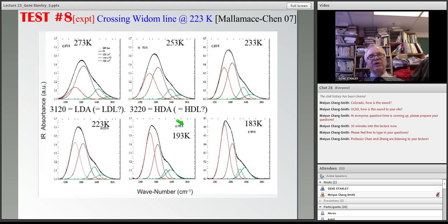And you know, one of the famous things for people who do spectroscopy, one of the famous things they do, always made me a little uneasy, is to decompose something that looks almost like a perfect Gaussian into many Gaussians. And that's what this shows. Here's one Gaussian, which has a peak at exactly the frequency, 3120 wave numbers, that low-density amorphous solid has. And as we argue, that should be exactly the same as low-density amorphous liquid, except for mobility. So there's the LDA peak. And here, at 3220, the brown curve is the HDL peak. HDL, why do I call it that? Because the frequency is the same frequency as HDA, which has been measured by many experiments by them.